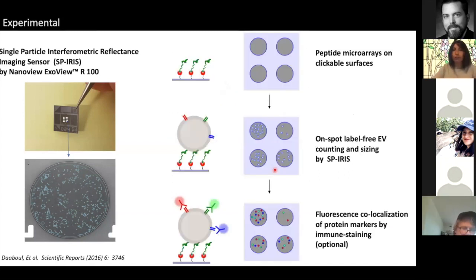So what we do from a practical point of view is to prepare our chips. That means we coat the silicon chips with our functional polymer. We spot the peptides. We know that they bind chemoselectively in an oriented way on the surface. And in this way, we produce our own peptide microarrays. Then the surface is incubated with a sample containing extracellular vesicles that are captured by the probes. The NanoView platform is able to label-free count and size by SP-IRIS technique the vesicles that are captured at each spot location.